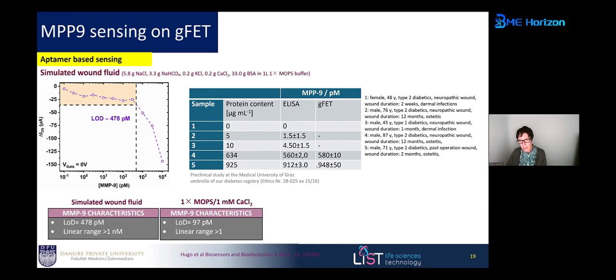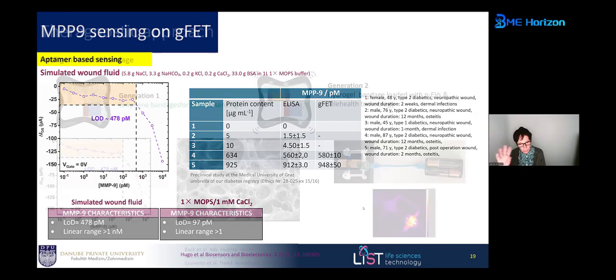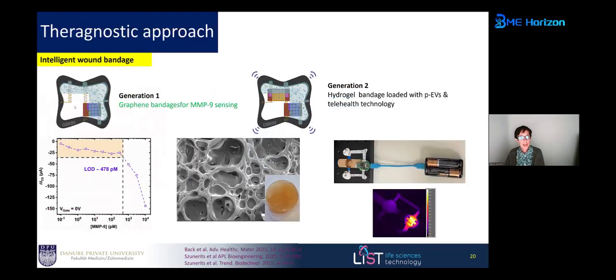So this is where the gFET actually seems to be competitive with the ELISA. We almost get the same concentration between our gFET and the ELISA, with the advantage that now we have a reading in 1 to 2 minutes. You can integrate these bandages onto the wound and get a direct online reading. But also an advantage of this approach is, and I know it gets a little bit out of sensing, but I will give you some idea of the importance of this type of device, you can not only measure,